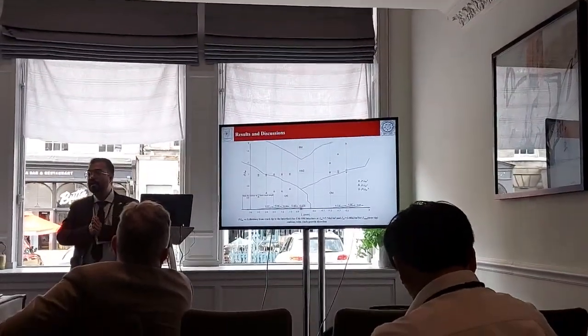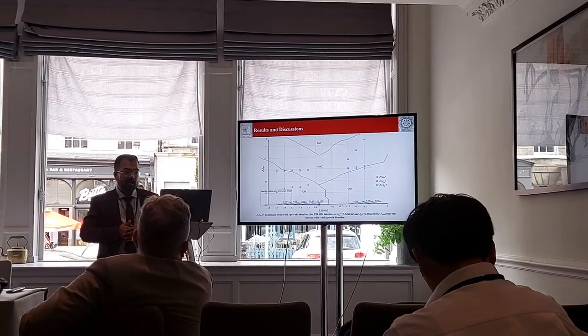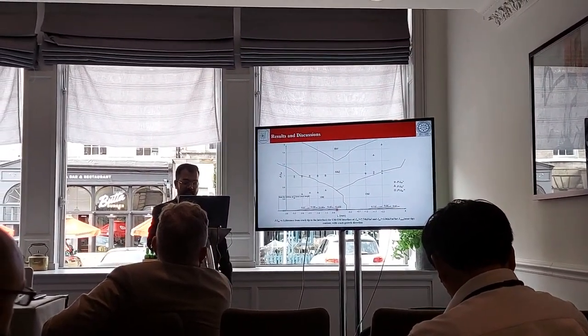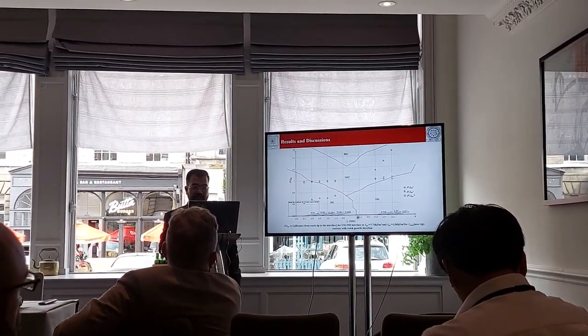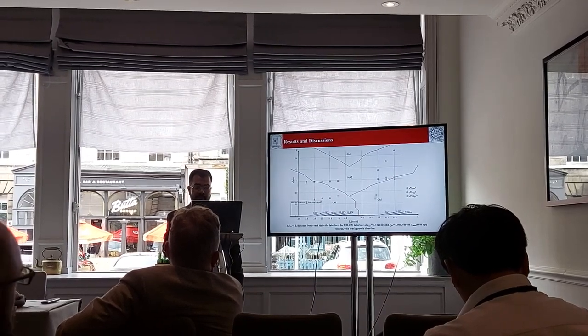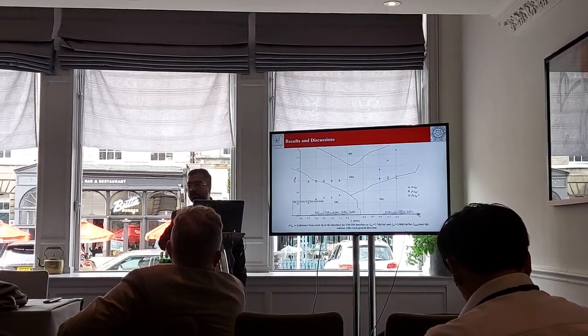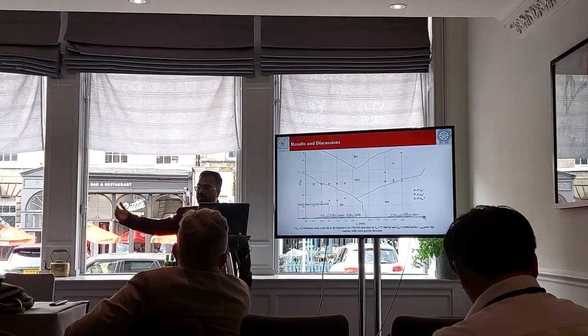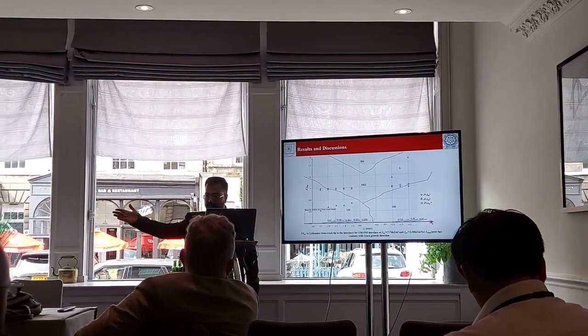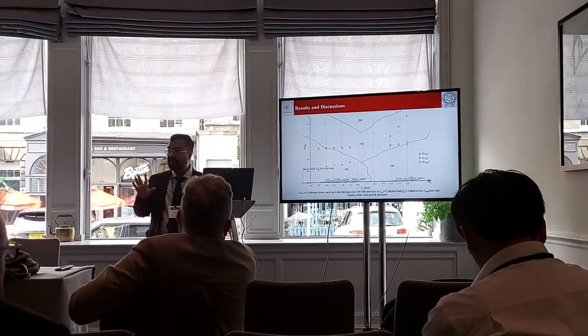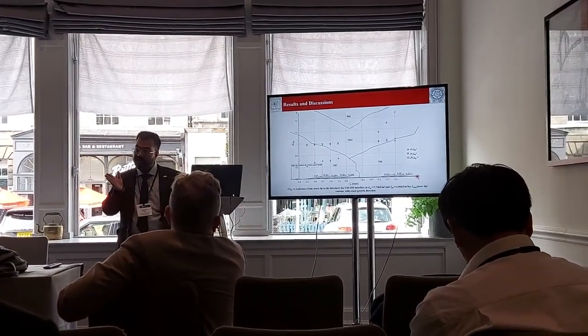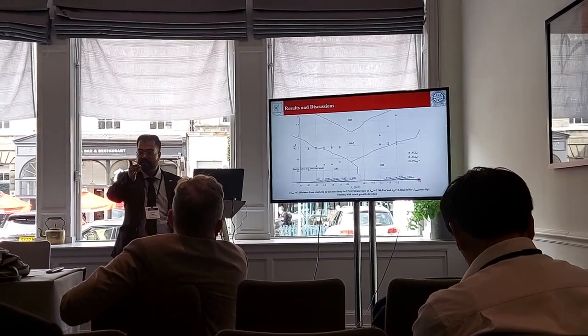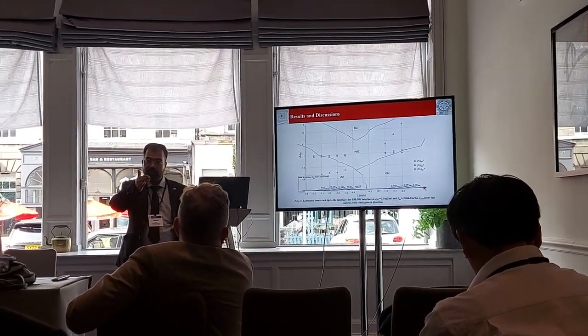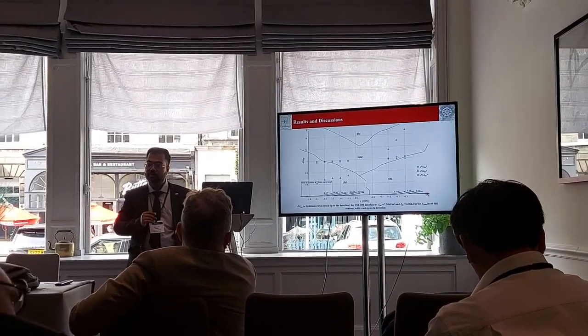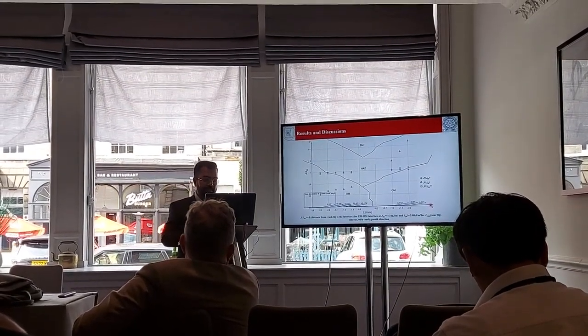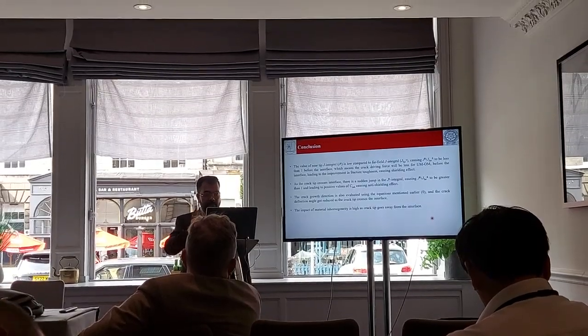So that is true because the crack is coming closer to the interface. But then it has a zigzag manner, and when it crosses this interface, it still has an influence because of this interface, and therefore it will drop down, and as it goes away from the influence of the interface, it will come back to 0. But this will not be the reality, because once the crack crosses the material resistance, it will start growing in that deflection direction. So that we have not considered here. For that, we will have to do damage modeling. So that's it. And so we conclude that.